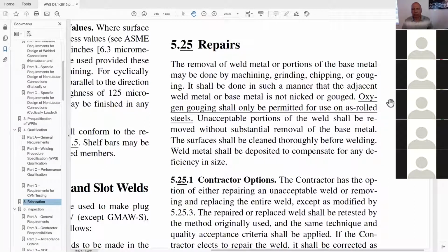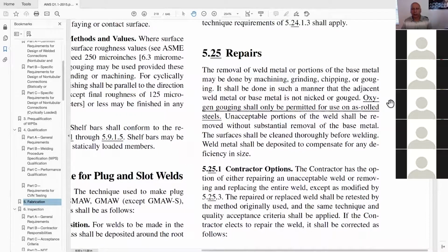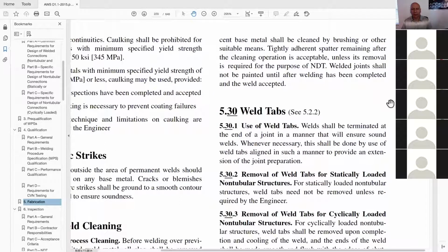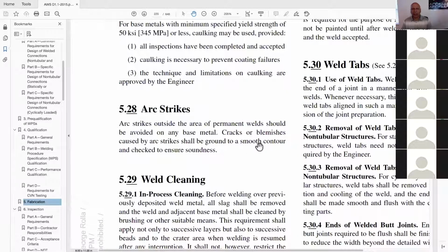We're pretty picky about arc strikes too, because arc strikes require repair. If we look at clause 5 here, arc strikes are required to be repaired and checked for soundness. So wait a minute. If a guy in a test strikes an arc somewhere, is he going to grind and smoothen it out and repair it? And then we're going to have to check for soundness. Well, that's not going to happen, because that means there was a reject and a repair required, and an inspection required before and after the repair. There are no second chances in a test. That would disqualify the welder if there was an arc strike on that test.